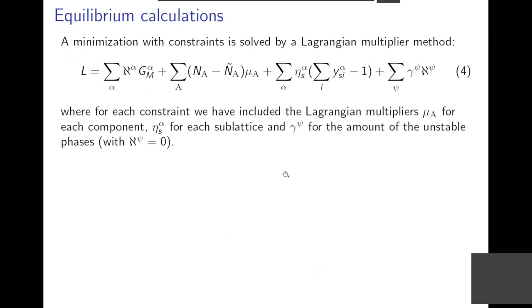And then to calculate the equilibrium, all software I know uses the Lagrangian multiplier method to handle constraints on the amounts. This is a prescribed amount of an element, and this is what you calculate for during a minimization. And this is, again, the amount of the phase. This is the Gibbs-Duhem relation for the phase. This is the constraint on, if you have sublattices, that the sum of fractions should be unity.